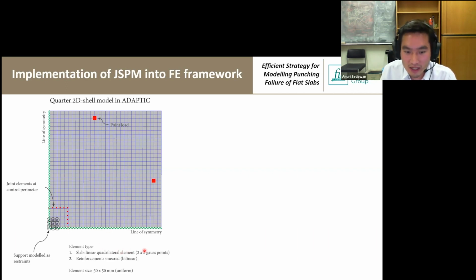We are using quadrilateral elements and a smeared approach for the reinforcement, and the element size is typically around 50 by 50. This size is a little finer than what people usually use for shells, but we need several joint elements along this control perimeter. So the element size is actually dictated by how many joint elements we want, because if you want to simulate redistribution, it is better to have more joint elements.